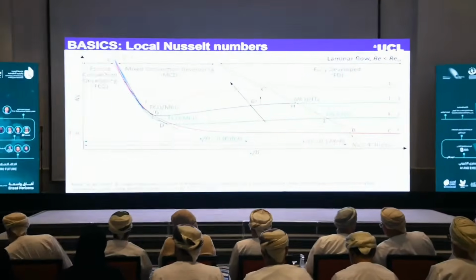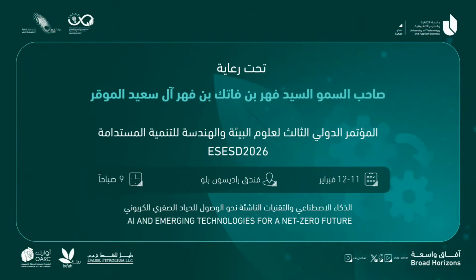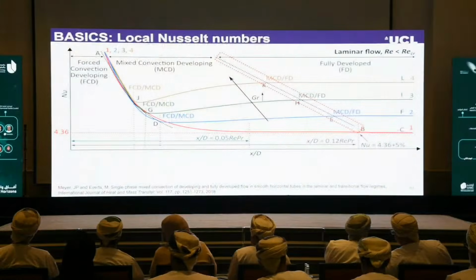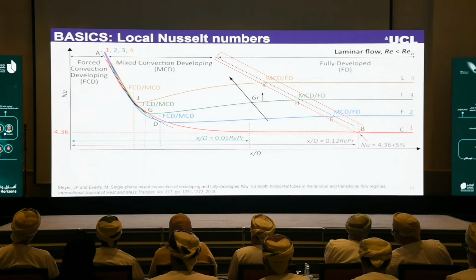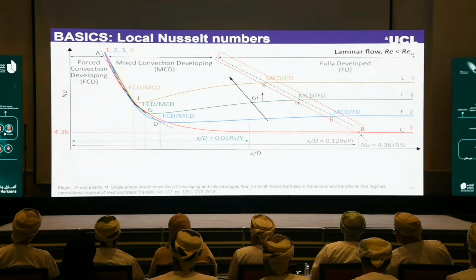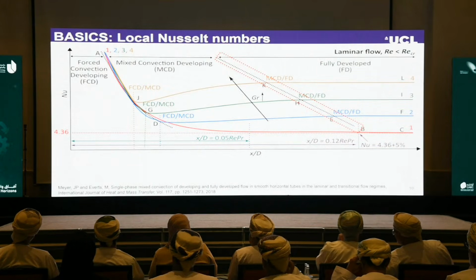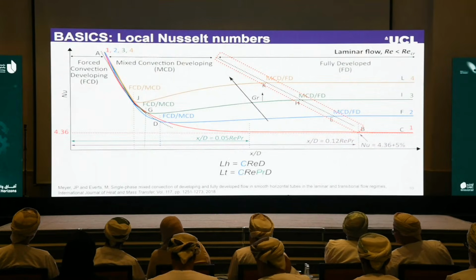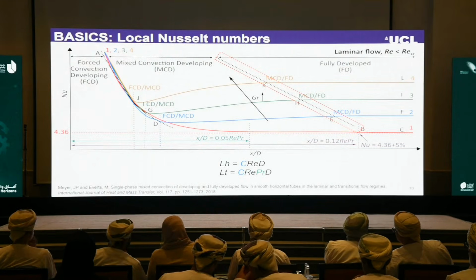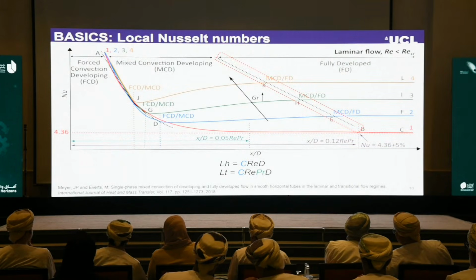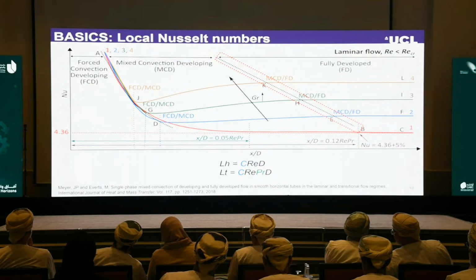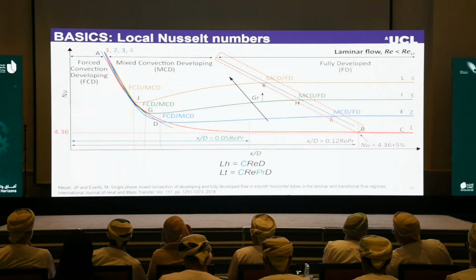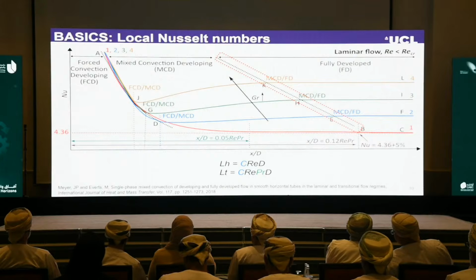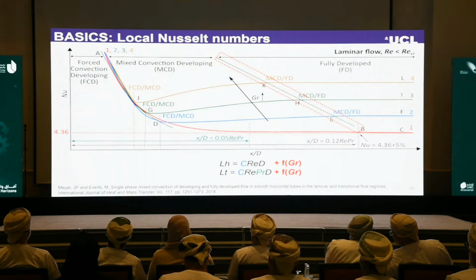And then a small detail in this graph, but one that should not be overlooked, is the boundary between the mixed convective developing region and the fully developed region. As we look at this graph, we see that it inclines to the left as we increase free convection effects. So this tells us something very important, and that is that the hydrodynamic and thermal entrance lengths, as we see them in our textbooks, cannot only be a function of Reynolds number, Prandtl number, and tube diameter. When dealing with mixed convective flow, which we basically find in all our heat exchanger applications, we also need to account for the Grashof number.